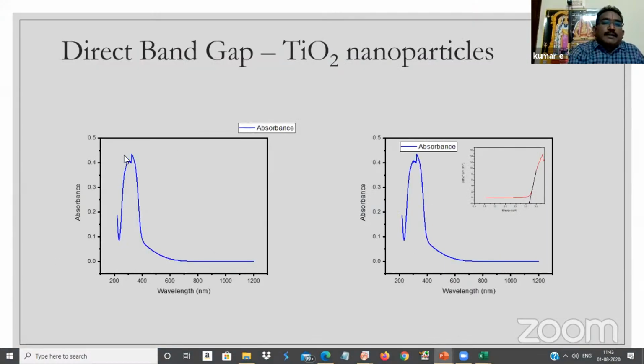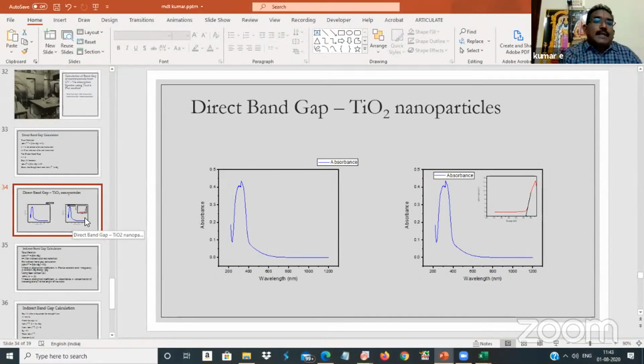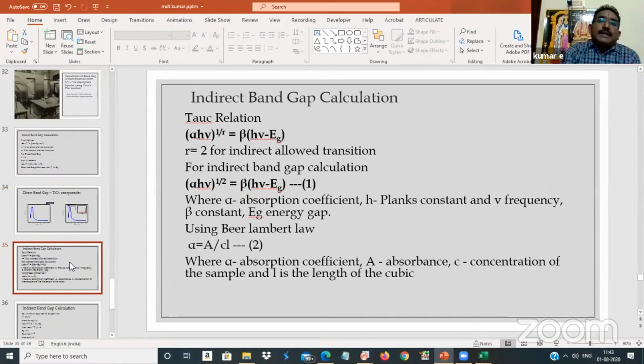So first we draw the absorption graph, then a direct plot. This direct band gap is exactly matched with the titanium dioxide nanoparticles. The direct band gap value is around 3.15. Actually the bulk nanomaterial is 3.2 electron volt. Here it is 3.15. So the direct band gap is directly calculated by using the Origin program. Next, to calculate the indirect band gap.